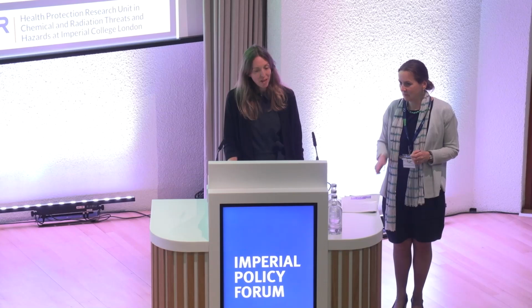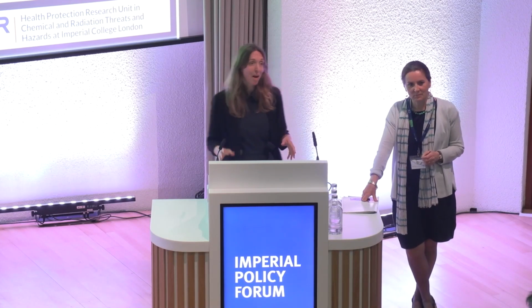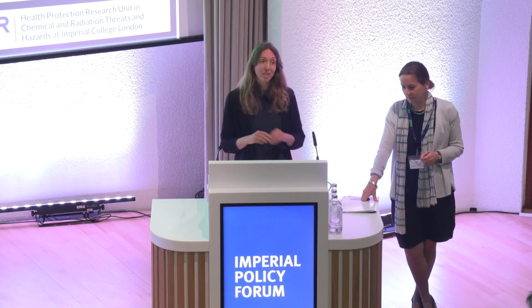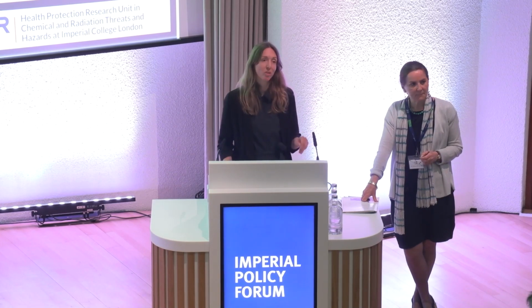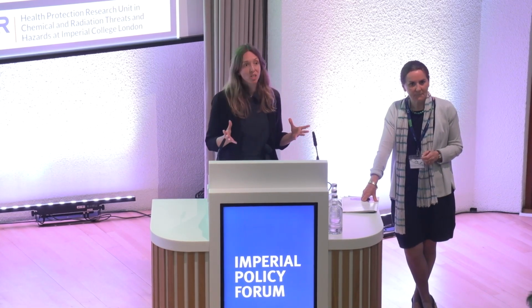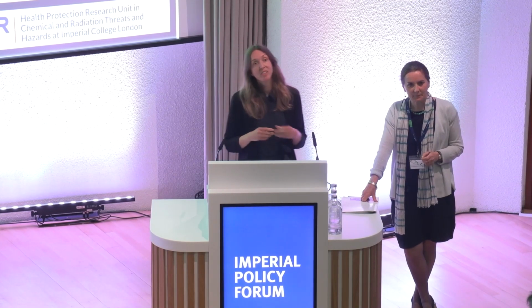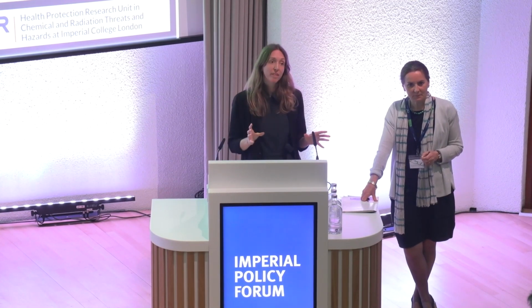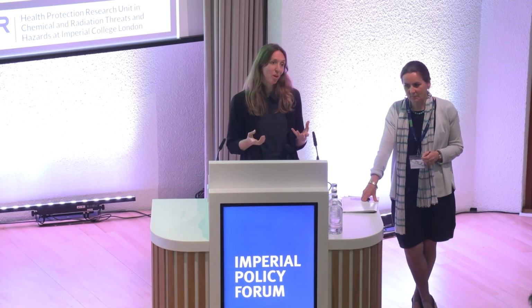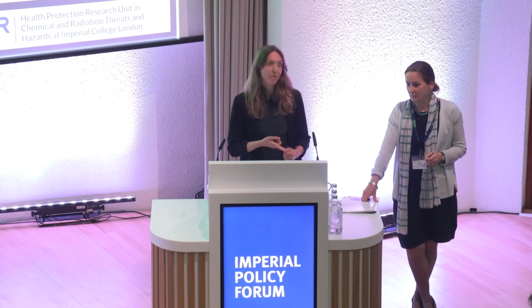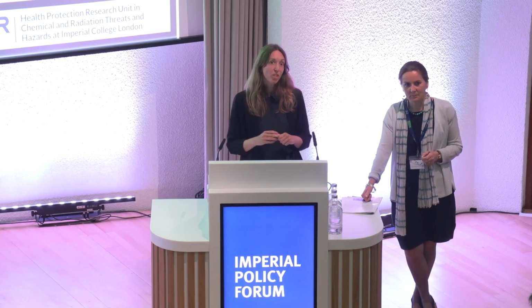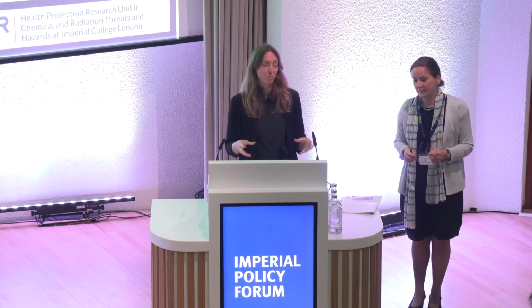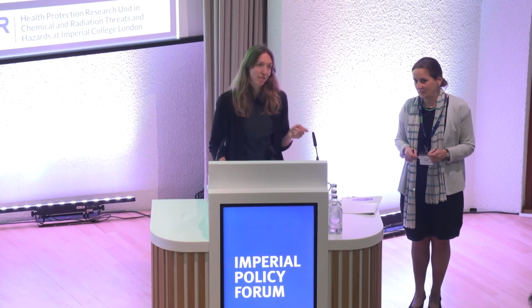I would say there's not much data. I think the data that we have are from in vivo studies, probably looking at polystyrene beads, quite historical studies, that were interested in particle kinetics in general. There is suggestion that uptake and accumulation in different tissues does occur, but it's very much related to particle properties like size, and surface chemistry. No studies have currently looked at microplastic fibers, microplastic particles, different types of plastics, and whether they're taken up and where they'd accumulate. But it's very likely that size is the really critical factor governing that.